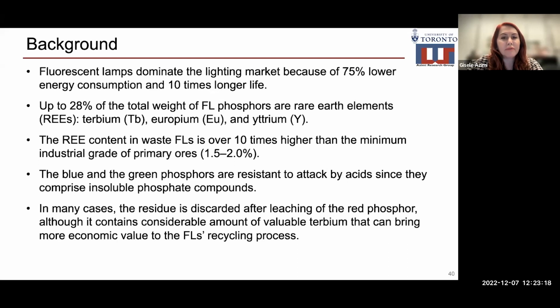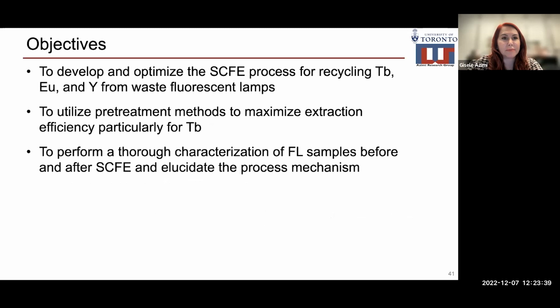The blue and green phosphors are resistant to attack by acid because they comprise insoluble phosphate compounds. In many cases, the residue is discarded after leaching the red phosphor, although it contains a considerable amount of valuable terbium that can bring more economic value to the fluorescent lamp recycling process.